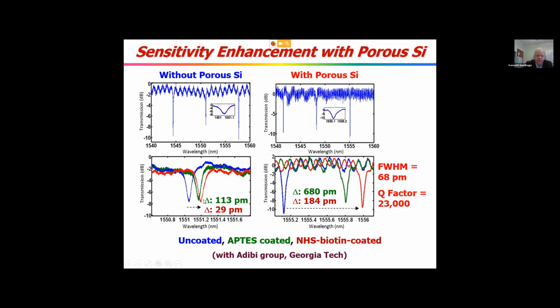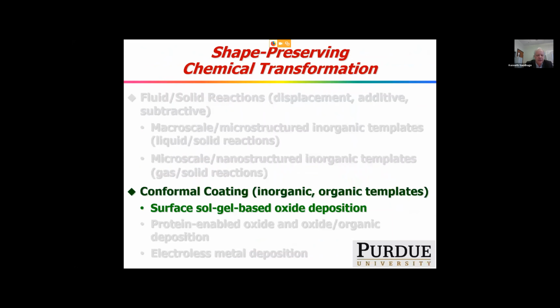When we put porous silicon with our process on the resonator, again, you have these massive drops in transmission at particular wavelengths, but now the shift that happens when you put the analyte on is about a factor of 6 higher, and we don't substantially lose the quality factor. And so this is a really nice way to make porous silicon on dense silicon for optical detection applications.